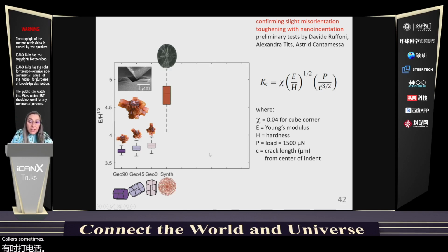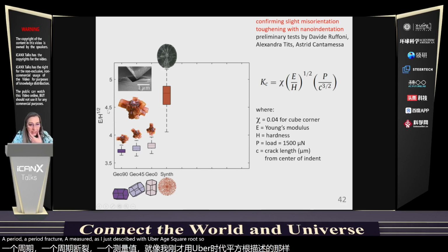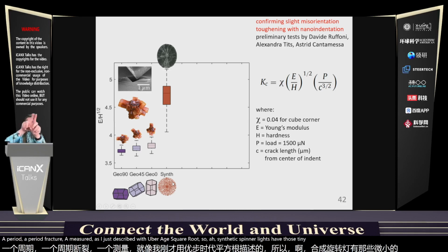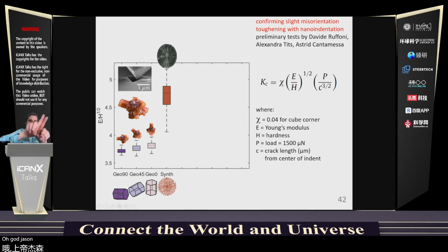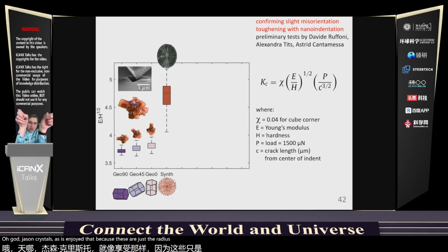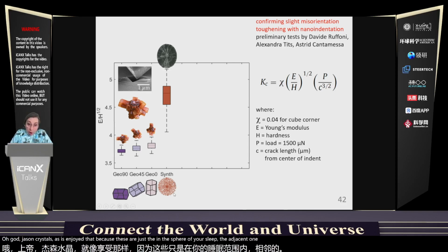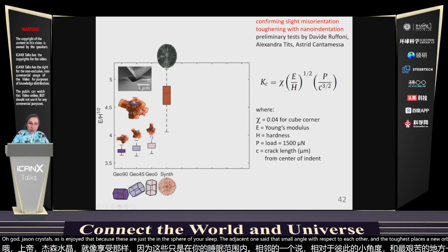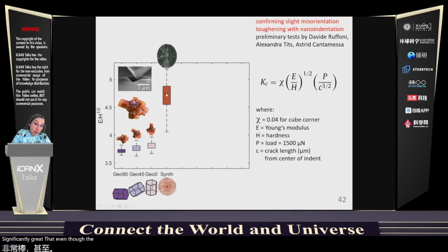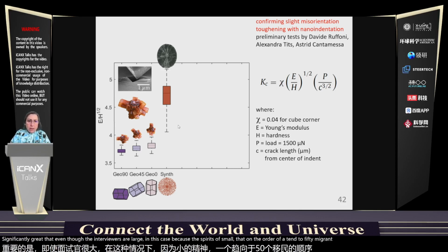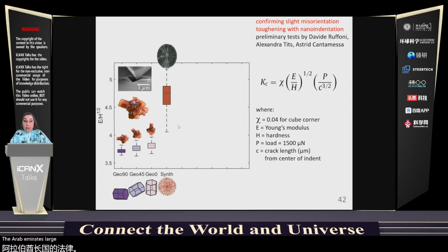Now, synthetic spherulites instead show this enormously larger apparent fracture toughness, measured as I just described with E over H square root. So synthetic spherulites have those tiny little misorientation angles of adjacent crystals, as is intuitive because these are just the radii in a sphere. Obviously, the adjacent ones have this small angle with respect to each other, and the toughness is enormous compared to the geologic one, significantly greater, even though the error bars are large in this case because the spherulites are small. They're on the order of 10 to 50 micron in size. The error bar is large, but the difference is significant.